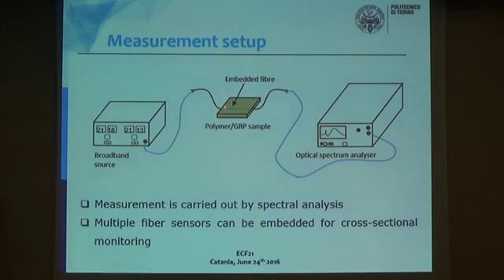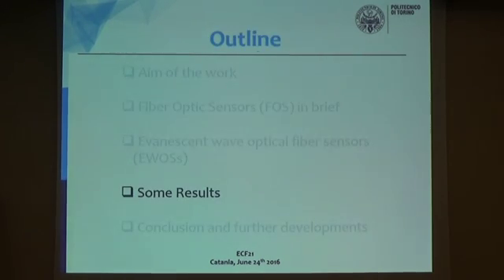The measurement setup is a standard source and detector arrangement. So you have a broadband source, in this case emitting in the infrared region. You have the sample and the embedded fiber, and an optical spectrum analyzer that makes the spectral analysis. It's possible to embed, as you have seen in the previous picture, several fibers, but you need to do a multiplexing system both at the source and at the detector, which can be a little bit problematic.